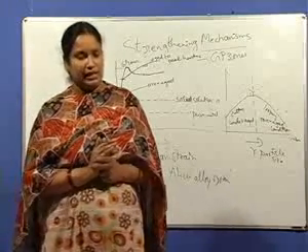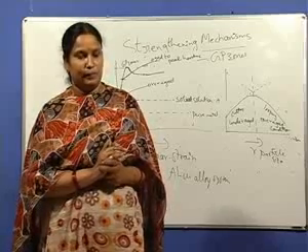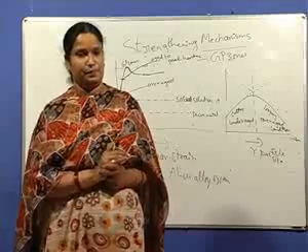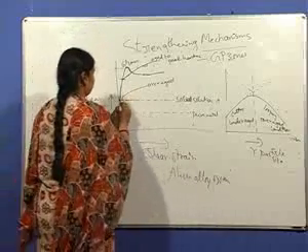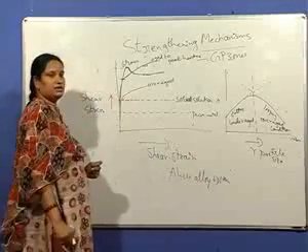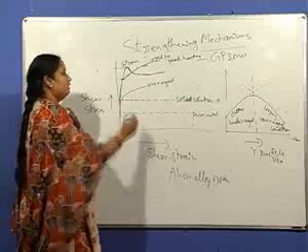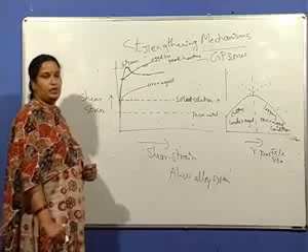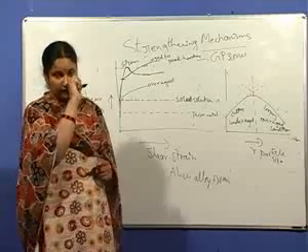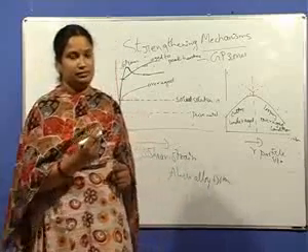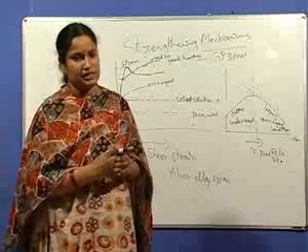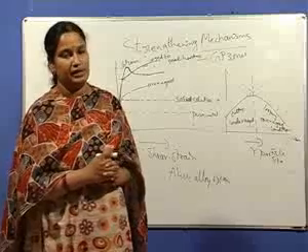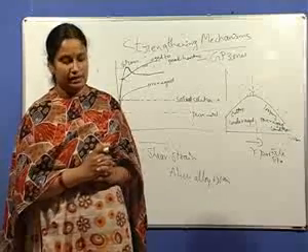Even though it shows a slight decrease in yield strength, the rate of strain hardening is very high. And for the case of overaged, the yield strength is lower, but the rate of strain hardening is also higher. Why? Because of the tangling of the dislocations, which increases the rate of strain hardening.